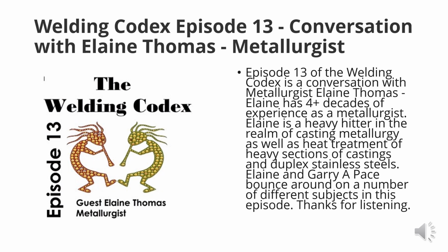So what you end up with is two different alloys essentially connected by, well, it's a galvanic cell is what it is, right? And so it's very easy for corrosion to just eat right through the material, going for those chrome depleted zones. And that's what sensitization is. To fix it, you take the metal up to about 2000 degrees. Again, chrome and carbon hate each other at that temperature. They break up. The chrome goes out there to fight corrosion in the matrix, and then you throw it in the water and freeze it in place. Don't let it form again.